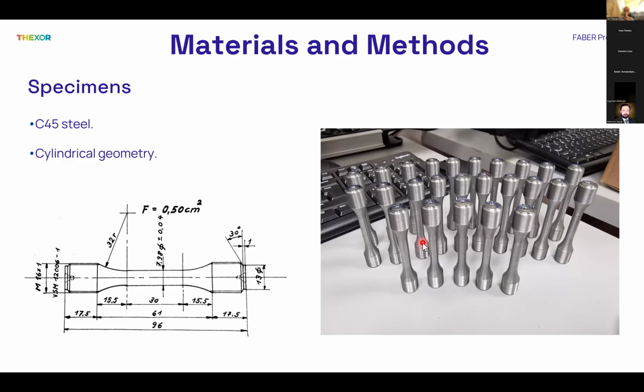The specimens adopted during the fatigue test are reported in this slide. The specimens were made of C45 steel, and the geometry is reported in these two pictures. A cylindrical geometry was adopted for the specimens.